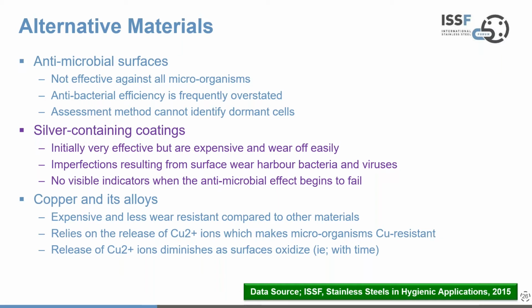So it's not without some challenges, even though there are some positives to antimicrobial surfaces. Similarly, silver-containing coatings, which are initially very effective, and you would argue better than stainless steels at the start, do wear off easily. So you've not only got a high cost to pay for these sorts of products, but you've got the challenge that wear brings over time, and the imperfections that result from surface wear harbour bacteria and viruses. And with silver containing coatings, you have no visible indicators when the antimicrobial effect begins to fail. So again, some challenges because the problems are not visible.